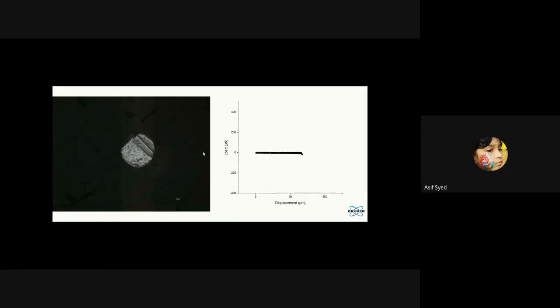This is done so fast in this video, you are not able to see how the size of the contact is changing. But normally when you replay it at a very slow speed, you can see how the size of the contact is changing. So that itself is a measurement where you are measuring the size of the contact directly. You also have the load displacement measurement where you can use the modeling to extract the numbers. So in this one simple experiment, you have a way of measuring the size of the contact independently, but also a way of measuring the size of the contact through the load displacement curve. That is the advantage.